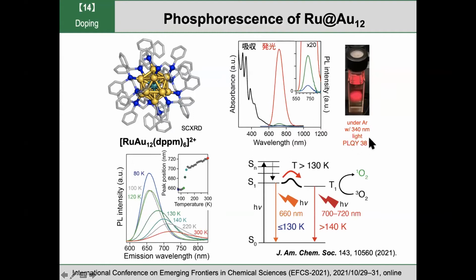And interestingly, this luminescence can be quenched by the presence of oxygen. So oxygen can quench this emission. This means that this emission can be assigned as phosphorescence. So this is a very efficient phosphorescent cluster. And if you reduce the temperature, the origin of the photoluminescence changes to fluorescence. But anyway, single atom doping can enhance the quantum yield of photoluminescence dramatically.